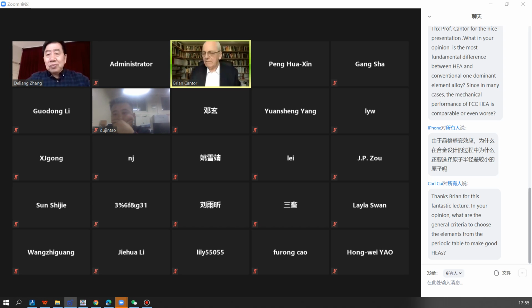Okay. Look, it's a balance. The special properties of the solid solution FCC alloys, the Cantor alloys, are caused by the local lattice strains. That's what makes the diffusion slower. It's what makes the dislocation slip more difficult, which makes the starting yield strength higher, even though it's face-centered cubic and has tremendous ductility. Just to repeat, because some people think it has bad properties compared to copper: you've got the same enormous ductility, but a much higher yield strength in the Cantor alloy. And that's all because of these local lattice strains.